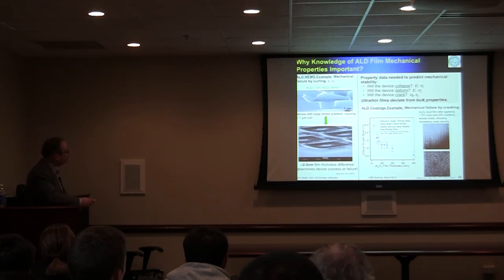And so to go from something like this to something that looks like this, which is the same device, it only took about 80 hours of clean room work and only 2 to 3 nanometers variation in film thickness. And it would be very nice to know ahead of time what the residual stresses were, so we could design for it, because there is plenty of information on how to design multi-layer structures based on residual stresses, but you have to know the stresses to begin with.